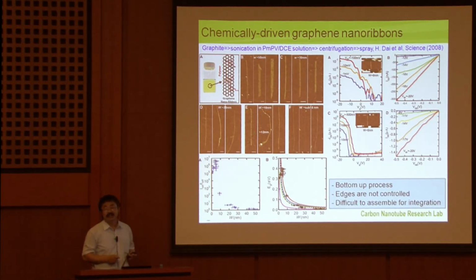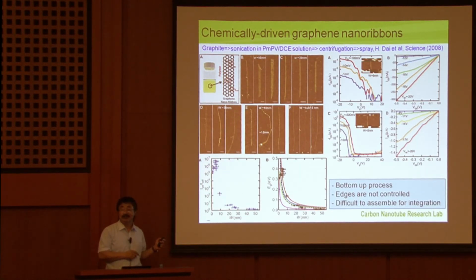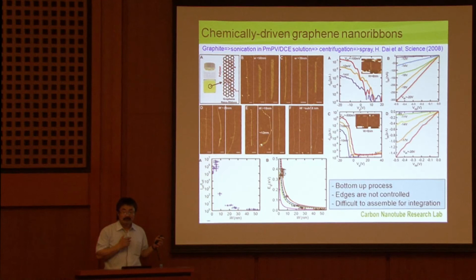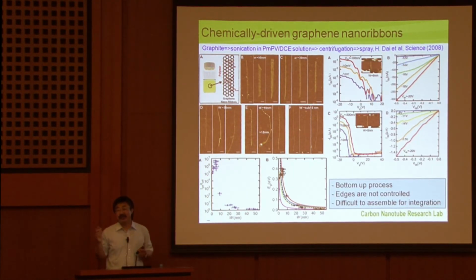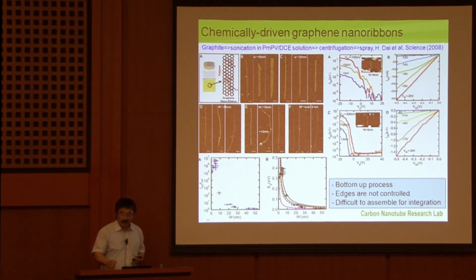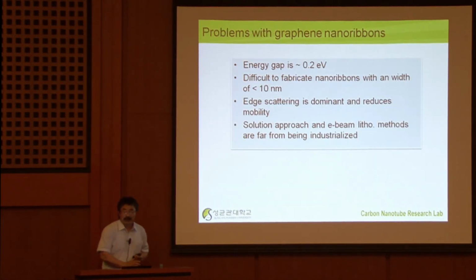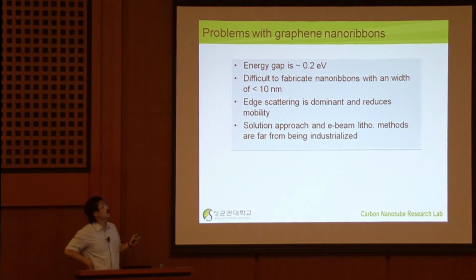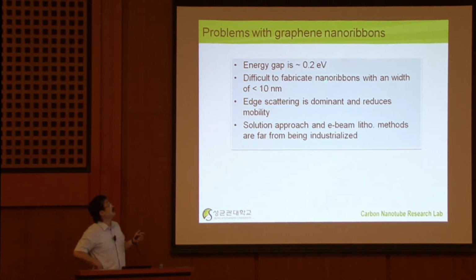Okay, like this one. And then you can connect this source and drain electrode, and then measure this, and you see this high on and off ratio, by chance again. So yes, it works in principle, but you cannot adapt this technology for real industry application. So in real industry application, you have to have some systematic way of producing nanoribbon. But again, no way. I mean, in this case, the best energy gap is like 0.2 electron volt, I mean, 200 milli electron volt. In this case, you have to have less than 10 nanometer, which is very difficult.